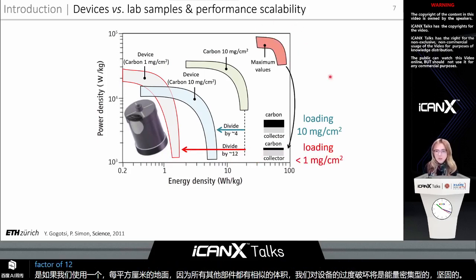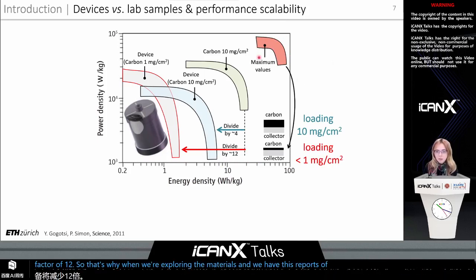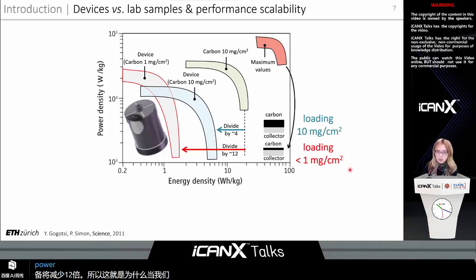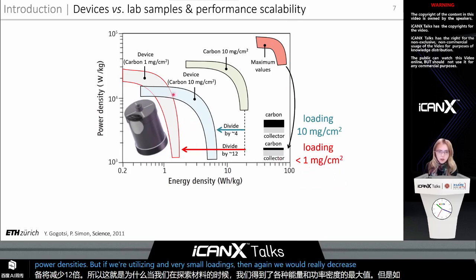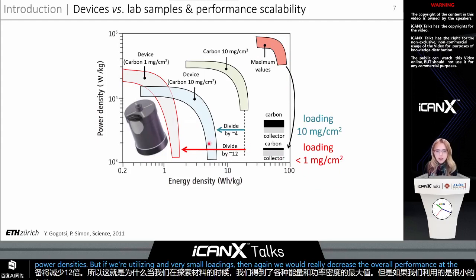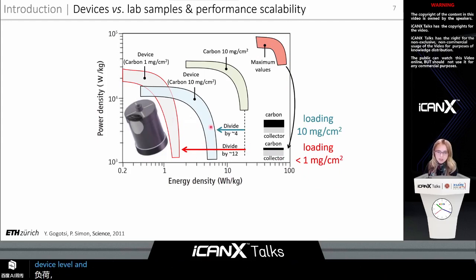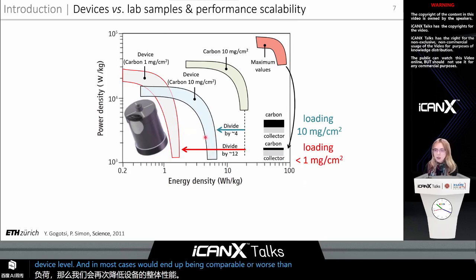So that's why when we're exploring new materials and we have these reports of very high maximum values of energy and power densities, but they utilize very small loadings, then again, we would really decrease the overall performance at the device level, and in most cases would end up being comparable or worse than a traditional state-of-the-art carbon-based supercapacitor.